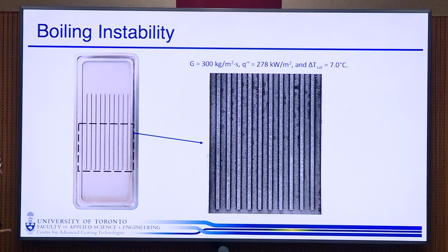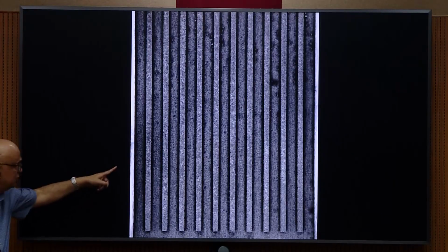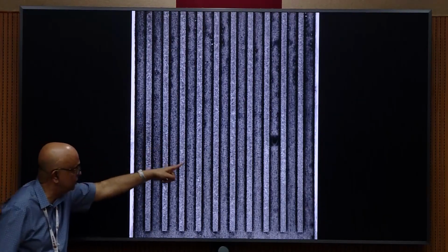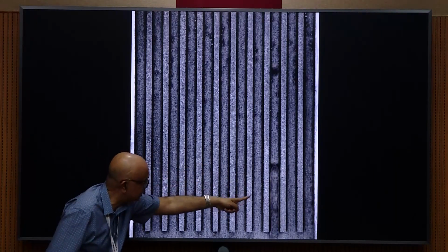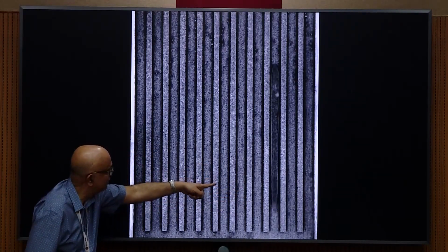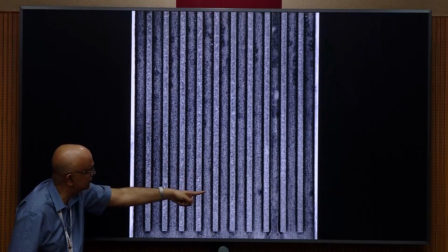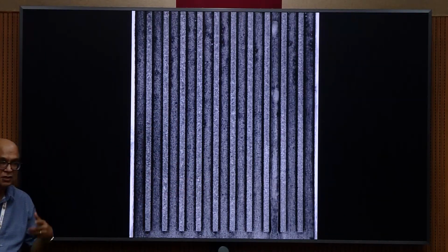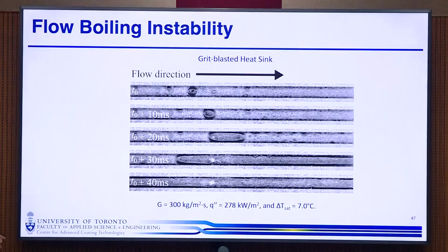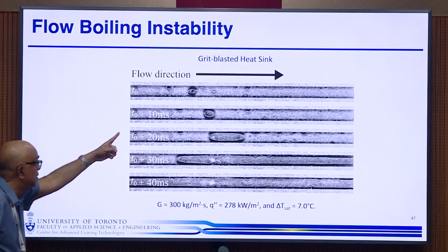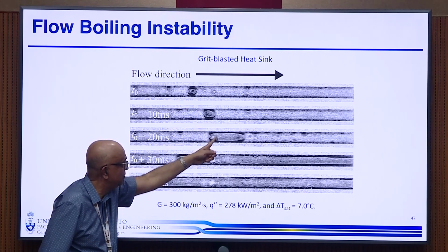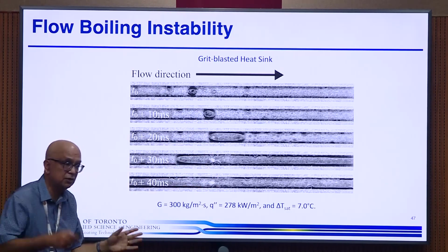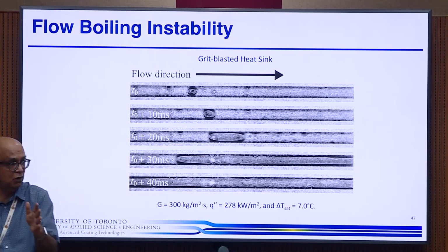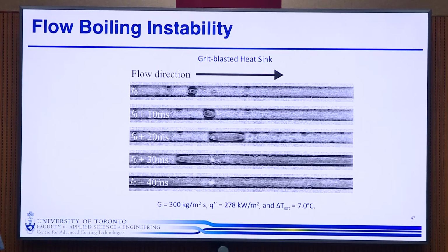Now, the limit on what we can do with this is because of the instability. So let me show this. So you can see the flow. Watch this one. So this bubble will suddenly grow and you get dry out. This is the incipient instability. So you've got a bubble growing, it fills the whole thing, this starts happening to other channels, soon you have no flow inside your heatsink at all.